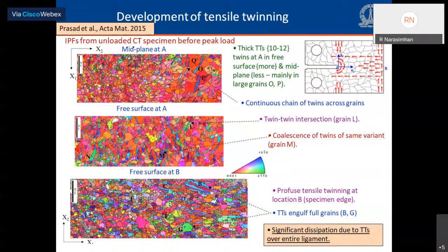In the midplane, if you look at the top IPF, you'll see that twins are present mostly in the large grains, like the ones labeled as O and P, and this is possibly because of reduced critical resolved shear stress for twinning in these large grains. There is actually a wealth of information about how twinning can influence hardening and fracture mechanisms by examining these pictures.